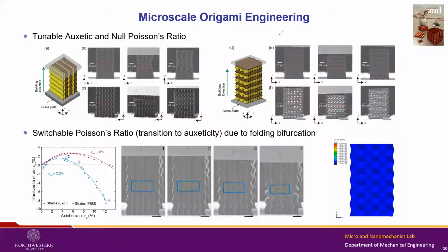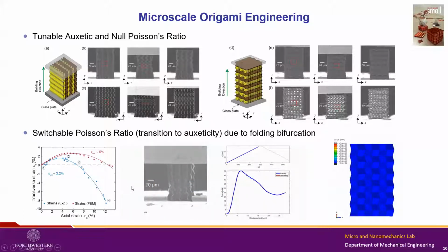So as you compress, they expand, but then there's a switch. Something happens in the structure, which is a folding bifurcation. As the panels fold, they come to a point where they can bifurcate, and that can trigger a negative Poisson's ratio. So as you keep compressing, the structure exhibits an auxetic behavior. So you have both these things, and this is a video of that structure, which has to start again.